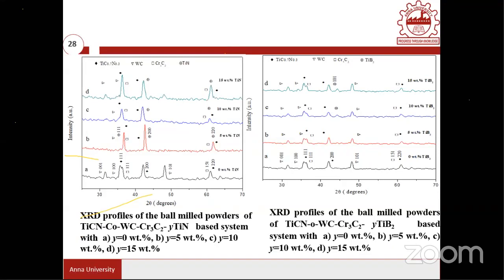Now, for the powders of every composition after milling, we have taken XRD to identify whether any new phases are formed, to verify whether the phases are retained as the original phases, or whether we have any new phase formation. Luckily, we don't have any new phase formation.